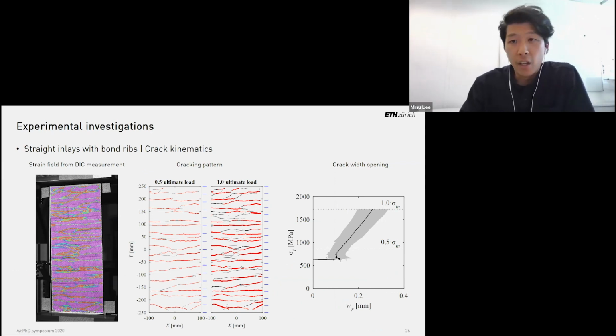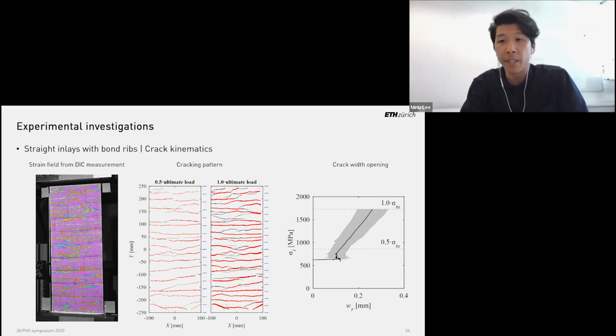Currently, we're having a closer look at the crack kinematics using the strain and displacement field from the digital image correlation. We can determine the cracking pattern and crack kinematics using the automatic crack detection and measurement software that was developed at our chair by Nicola Gheri and Jaime Mata Falcon. And this serves as an estimation of the average crack spacing and also for measurements of the crack width, as we can see on the right side.